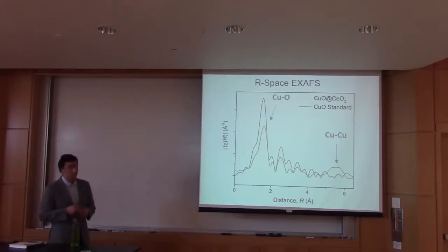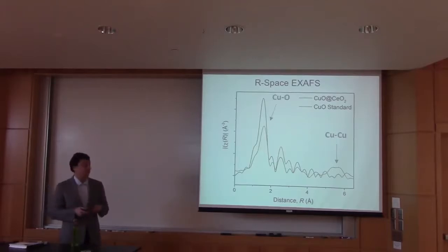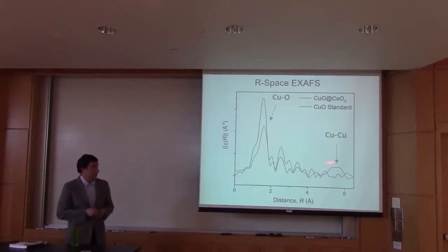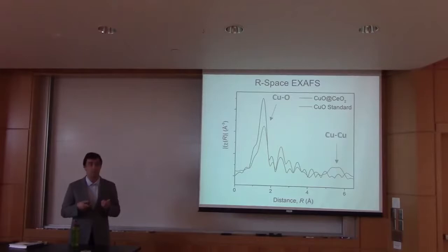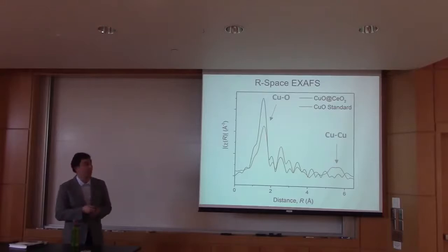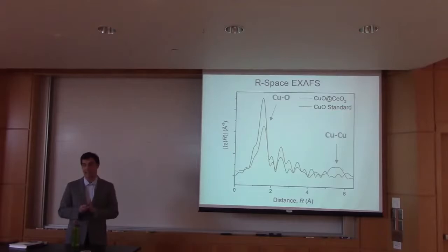We also have this copper-oxygen scattering distance, which is prominent in both spectra. Since we have copper oxide in both of our samples, we would expect this. And looking at this, it's not the most helpful in showing the absence or presence of these copper oxide domains or of these copper-copper scattering peaks. So I'm going to present this data another way and do a wavelet transformation of this data, where we're going to take the R-space data and turn it on its side and plot it against the K-space data.